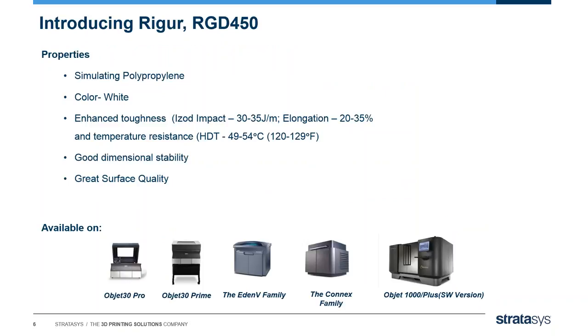So let's talk about Rigur. The order number is RGD450, and let's talk about its properties. Very important, Rigur is simulating polypropylene. It is of course not polypropylene material, but like all PolyJet materials, it's simulating a specific plastic, and here we're simulating polypropylene. The color is white and Rigur shows an enhanced toughness with a higher Izod impact and an elongation at break between 20% and 35%, and a temperature resistance, what we call HDT, of 49 to 54 degrees C. Rigur shows a very good dimensional stability and a great surface quality.